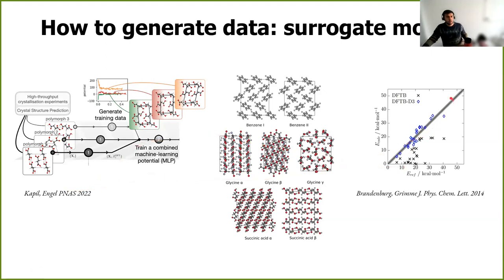So in this paper, what we really did was that we used DFTB and performed a large number of path integral MD calculations for all of these polymorphs, giving us a huge data set of structures. And with that pool of data, we were able to select, using some data-driven strategies, the most important 1,000 points, and on those 1,000 points, we were able to do DFT calculations. So thereby, using a much cheaper model where we could use molecular dynamics and path integral MD at a cheap cost, we were able to thoroughly sample the configurational space of interest for all of these molecular crystals, right? And that allowed us to get 1,000 really distinct points on which we could perform our DFT calculations.